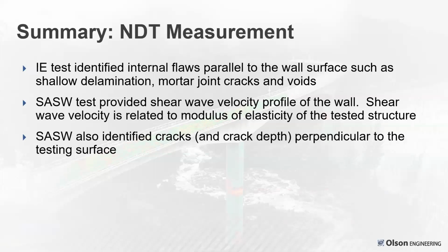So in summary, the NDT measurements: the impact echo test identified internal flaws that were parallel to the wall surface, like shallow delamination, mortar joints, cracks, and voids. The SASW test provided shear wave velocity profiles of the wall. The shear wave velocity is related to modulus of elasticity of the tested structure, and surface waves also identified cracks and crack depths perpendicular to the testing surface.